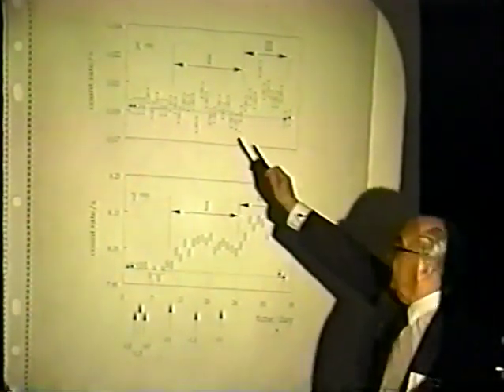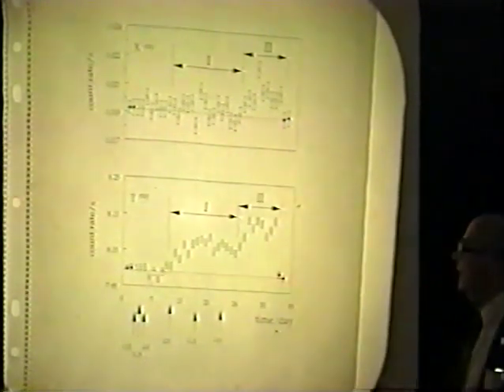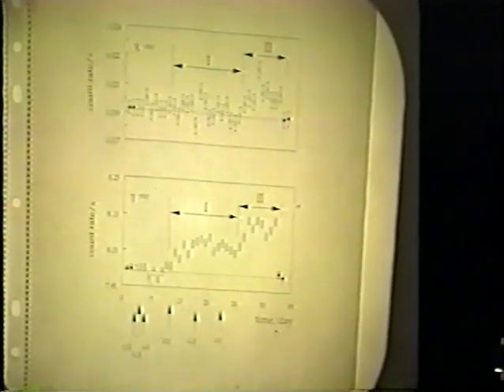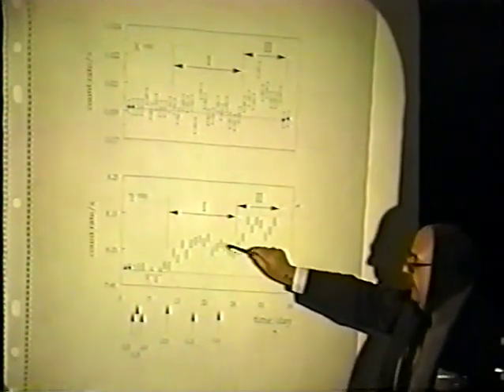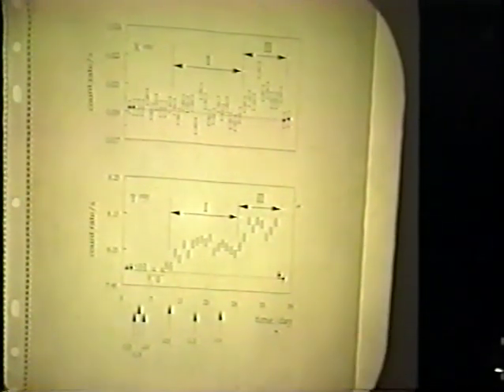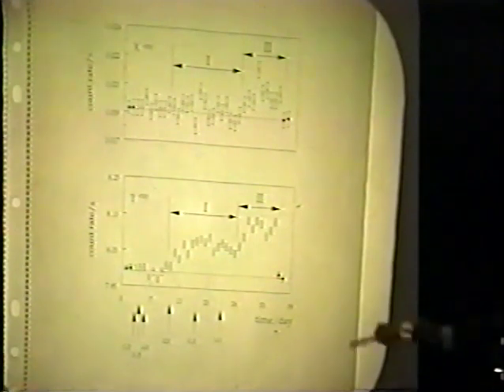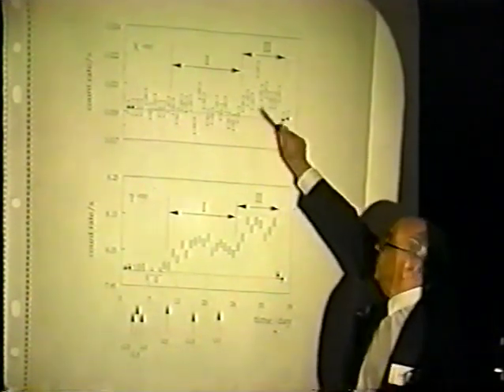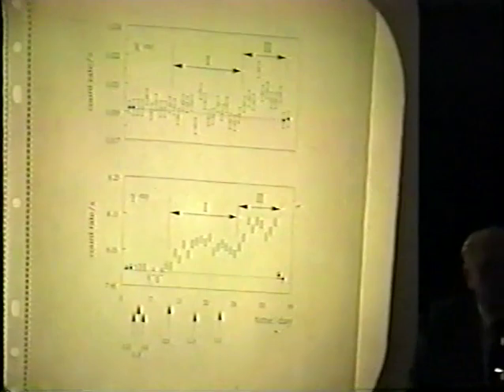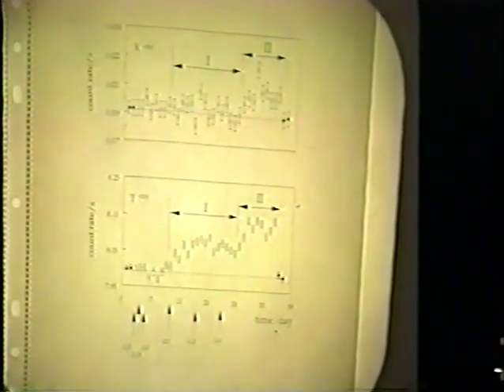Now we don't see it here in this one. Well, apparently the radiation is very soft, and we couldn't see it probably because of attenuation. But if we increase the current as we have done here, you can see both increased. So it appears that the amount of emission somehow is governed by the current, by the conditions that you impose.